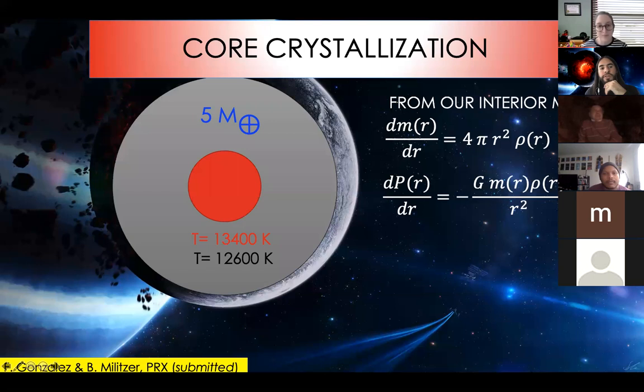So if we consider a very basic model for a super Earth with just a silicate mantle and pure iron in the center, then you have to have a model to predict what the pressures would be here, right? So we're talking here about pressures of 2000 gigapascals. And then the natural question is, does iron freeze? At what temperature does iron freeze for 2000 gigapascals? And then the core mantle boundary here would be at a lower pressure, say 1000 GPa. And at what temperature does iron freeze for 1000 GPa?